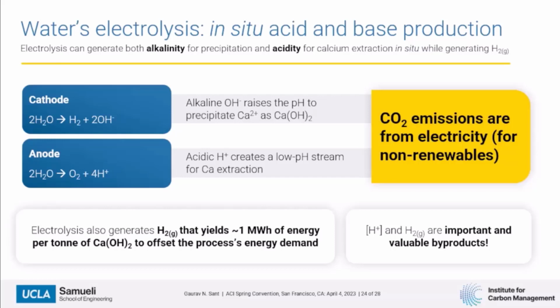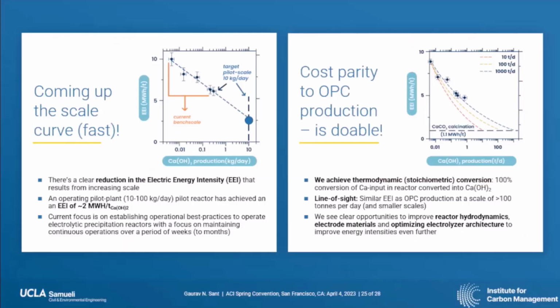Keep in mind, because you're running an electrolysis process, one of the things that's really important is you get about a megawatt hour of energy out of the process in just hydrogen alone, right? This is really quite attractive because this allows you to reduce the process's energy demand. But more importantly, if you're producing something like hydrogen, you can use it to power a traditional cement kiln. So keep in mind, effectively everything that you get out of an electrolysis process is actually really valuable because you can use all of it.